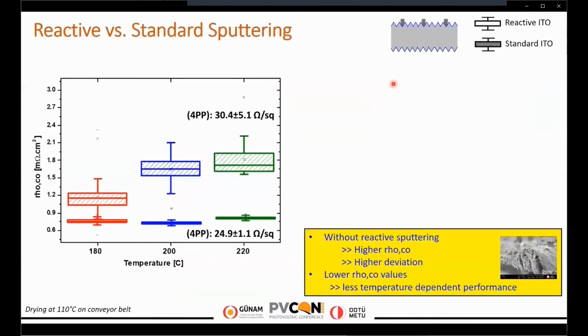Here we investigate the impact of oxygen partial pressure during ITO sputtering on contact resistivity with low temperature paste. In this experimental set, we also investigate the impact of curing temperature on the contact resistivity results. For all these studies, drying temperature is 110 degrees Celsius. We only change the curing temperature.